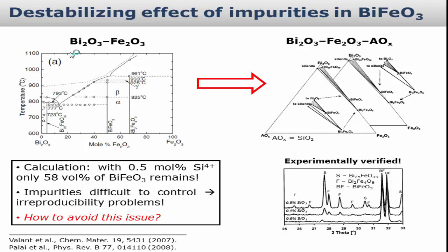So this is the phase diagram. And the problem is, since this triangle is very stretched, just a bit more silicon oxide will have a huge influence on the composition, just because the triangle is very tiny. That was also confirmed experimentally, and I think this is one of the main problems, among others, in the reproducibility of bismuth ferrite, because taking care of impurities and controlling their amount and type is usually very difficult. So how to avoid this issue? Well, the first thing is to really take care about impurities. Go very carefully when you prepare the oxides.